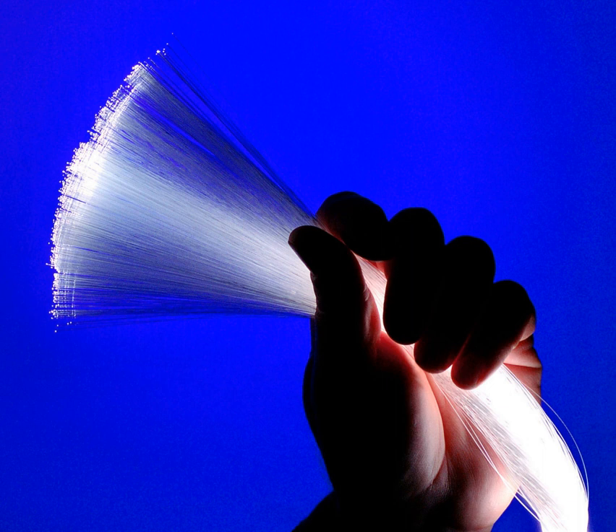Silica glass can be doped with various materials. One purpose of doping is to raise the refractive index, e.g. with germanium dioxide or aluminium oxide, or to lower it, e.g. with fluorine or boron trioxide. Doping is also possible with laser active ions in order to obtain active fibers to be used, for example, in fiber amplifiers or laser applications. Both the fiber core and cladding are typically doped, so that the entire assembly, core and cladding, is effectively the same compound, e.g. an aluminosilicate, germanosilicate, phosphosilicate or borosilicate glass.